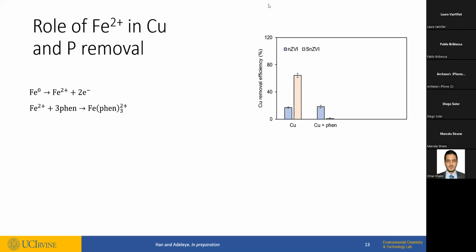So here's a summary of what we found. When we repeated the experiments, we found the same results, but when phenanthroline is present, there's no impact on removal of copper by NZVI, but the removal of copper by SNZVI was impacted. And that led us to really conclude in a way that the removal of copper by NZVI is primarily through reduction.